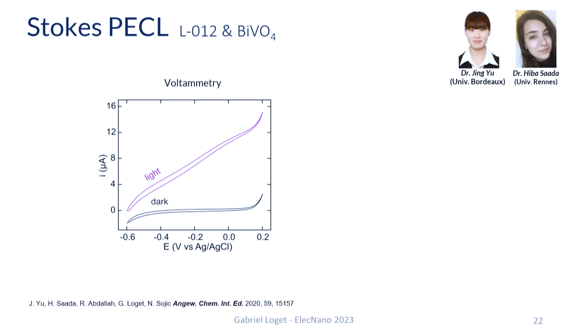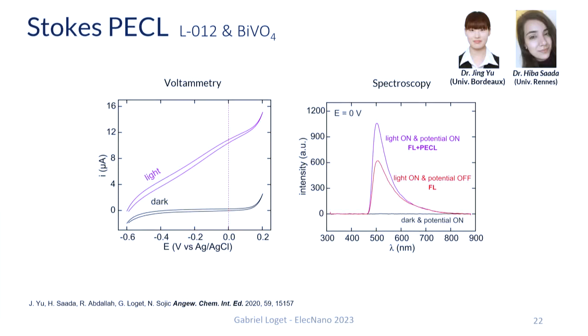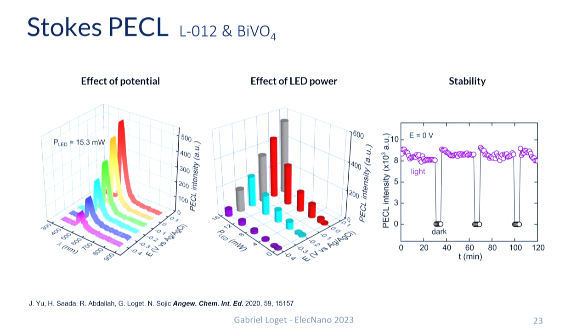Here you see the cyclic voltammogram for this system, bismuth vanadate in the ECL electrolyte. In the dark we have no current. Under UV illumination we have photocurrent. If we apply a potential to this electrode of 0 volt versus silver chloride, these are the spectral characteristics we obtain, the purple spectrum here. The red spectrum was obtained in open circuit conditions. So we see the fluorescence of our luminophore, but when we apply this potential, you see that indeed intensity is increased. So it's a way to control the luminescence intensity. We studied different parameters and showed that we can control the amplification using the potential we apply at the electrode and the power input of the LED, and this system was stable for a couple of hours.